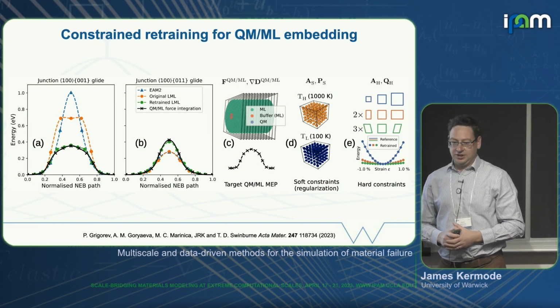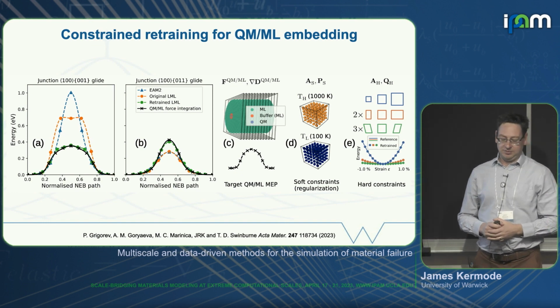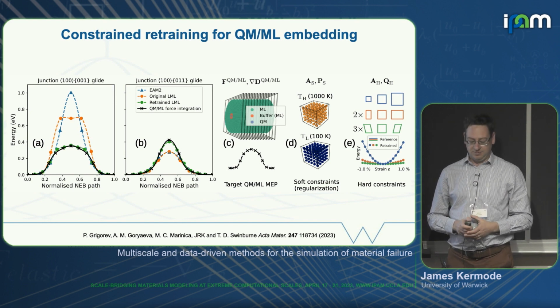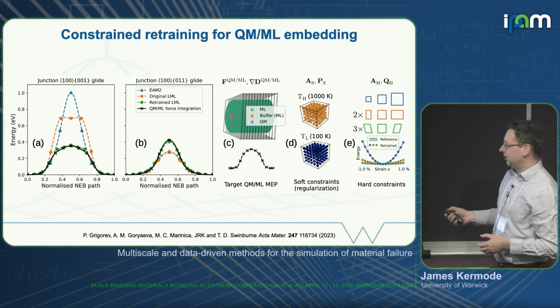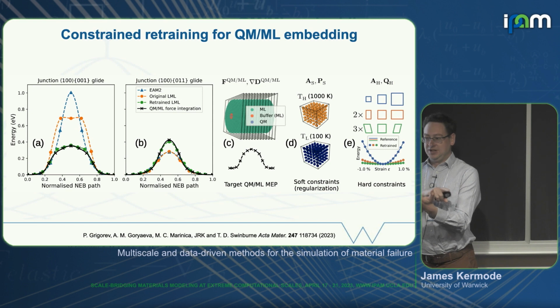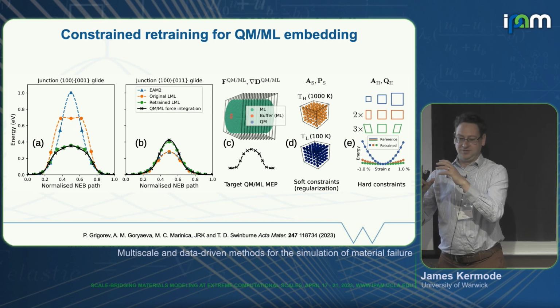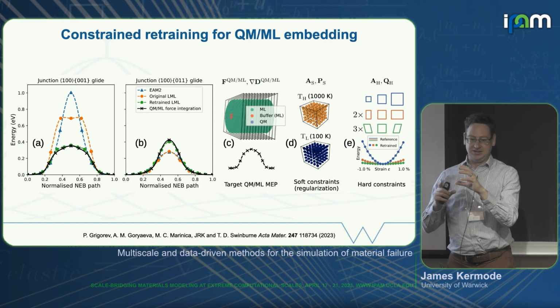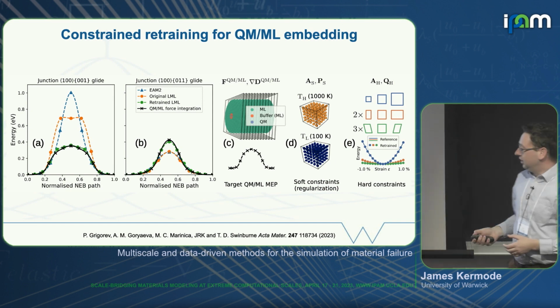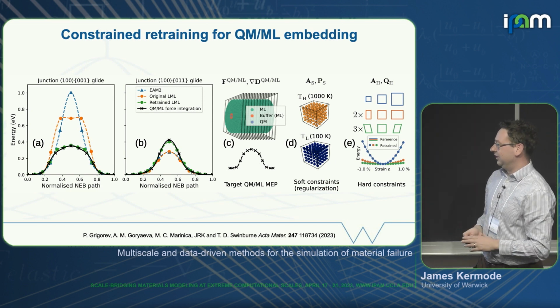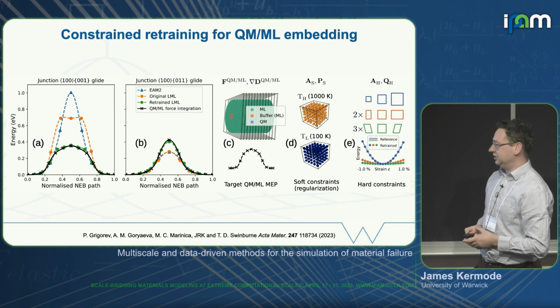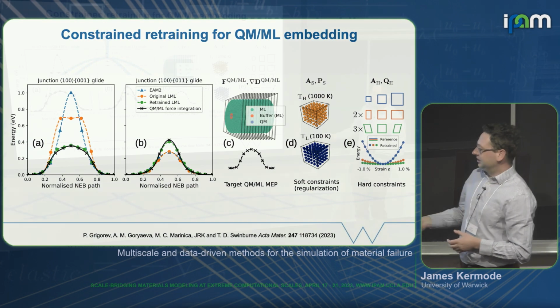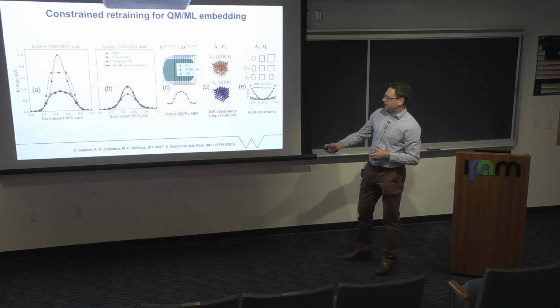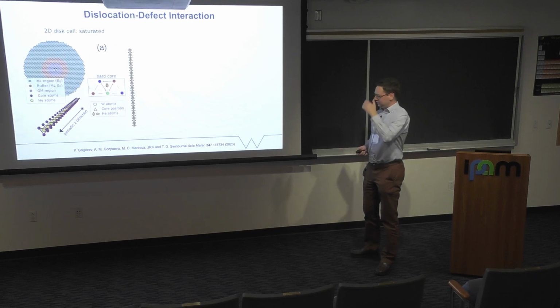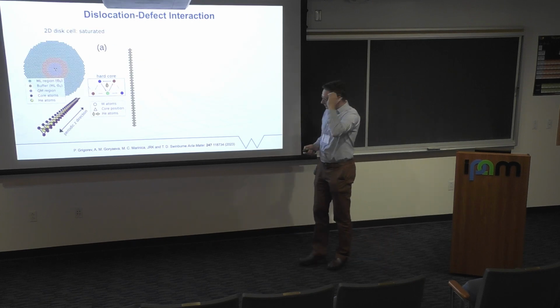We have to do it a bit carefully because we need to preserve some properties of the potential so that it's still suitable for embedding. In particular, we have a hard constraint on the elastic properties to prevent reflection of phonon waves at the interface between quantum and classical regions. We need to have a really good elastic matching there. We also use some soft constraints to generally prevent the potential from changing too much when we update it. And this works well. You can see after retraining, the potential alone describes the glide process very well. And so then we can go on and do some more interesting science with it.